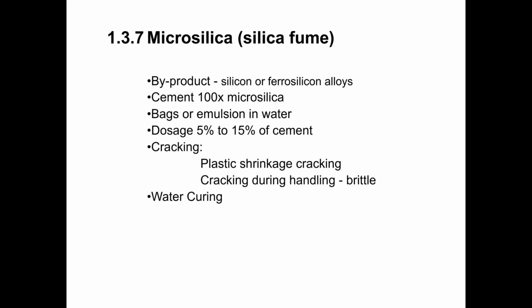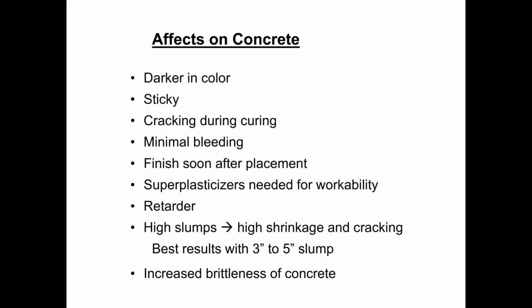So some other things to keep in mind when using microsilica are shown here on this slide. It does produce concrete that is darker in color. It's significantly darker than the cement, so it will be a darker colored concrete. The concrete does tend to be sticky. It's more difficult to work with in the plastic state. You have a greater potential for cracking during curing because of the rapid loss of moisture on the surface of the concrete and that minimal amount of bleed water that will be present.